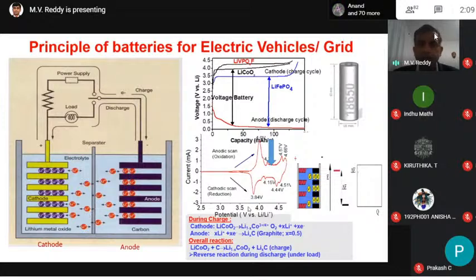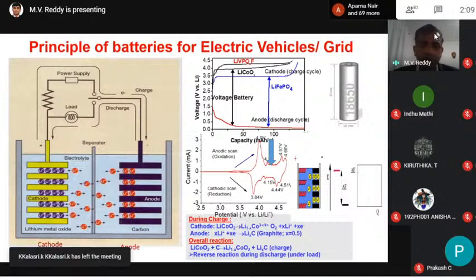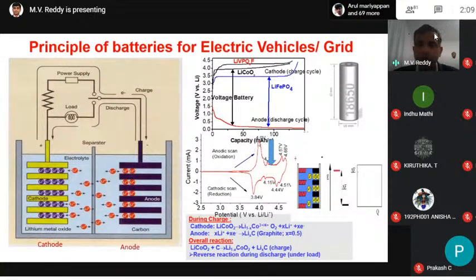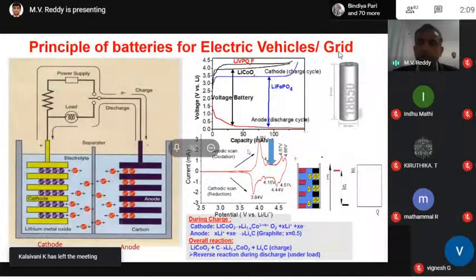So for example, this is a cyclic voltammetry graph, current versus potential, assuming this is a cobalt oxide. Here cobalt is in 3 plus. Once you remove lithium, cobalt goes from 3 plus to 4 plus, which we call oxidation. Reduction means going back from 4 plus to 3 plus. That's why we call it the redox couple. In the galvanostatic plot, we plot voltage as a function of capacity. As you can see, we get almost the same potential, around 3.9 volts.